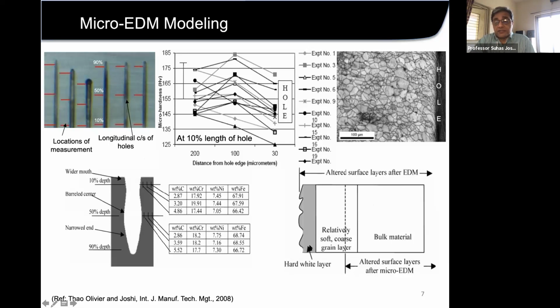This schematic tells you what exactly it is. If you take a regular EDM process, you will find that there is a damaged zone from this point to this point. So you have a hard layer, then a soft layer, and then the bulk material. So you have an excessively damaged surface in the EDM process. But in case of the micro EDM process, we hardly found any white layer, and we found just a small reduction in the hardness near the hole wall.